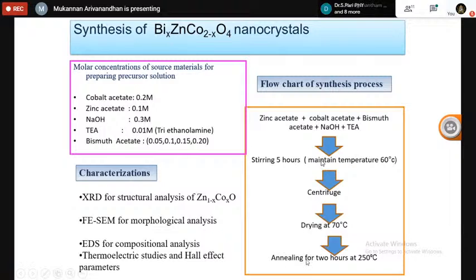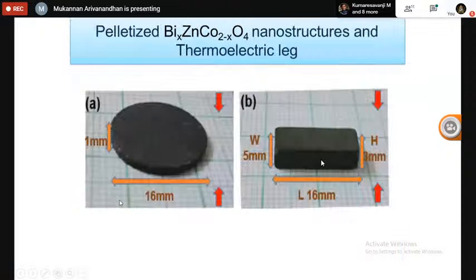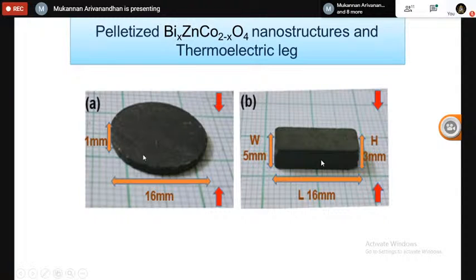Once we have the synthesized powder, we make it into a pellet and study the thermoelectric characteristics. These are the nanostructured material-based pellets. We make the pellets in different shapes, circular pellets and thermoelectric legs. If you have thermoelectric legs like this with optimized properties, then you can go for devices with a combination of p-type and n-type thermoelectric legs. Although it looks like a bulk, at the micro or nano level it contains a lot of nanostructured grains.